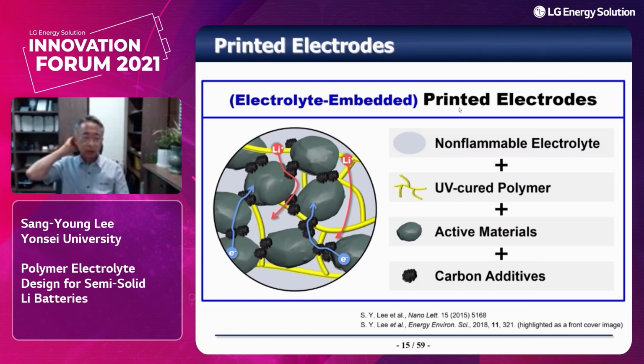Based on this understanding, we have further extended our concept to fabricate the printed electrode. The important point here is that the electrolyte should be embedded inside the electrode. Please take a look at this cartoon. In addition to active materials and carbon additives, we have incorporated the non-flammable electrolyte described previously, along with the UV-cured polymer.